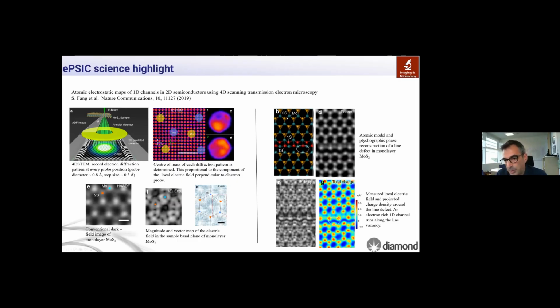So this is an example of some of the low dose electron microscopy they do on semiconductors when they look at line defects. And actually the reconstruction that we are using to look at this particular material is exactly the same as what we developed for X-ray science.